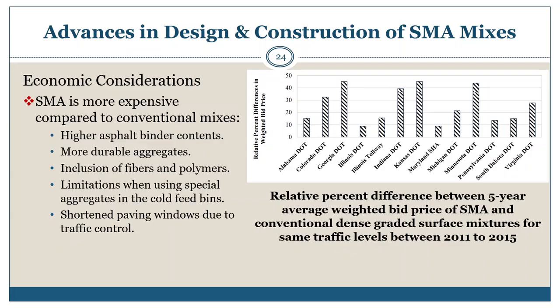Just about all agencies have reported that SMA mixtures are consistently higher in terms of initial cost than conventional dense graded mixes because of the higher binder contents, more durable aggregates, inclusion of fibers and polymers, limitations when using special aggregates in cold feed bins, and shortened paving windows due to traffic control itself. The relative difference between a 5-year average unit bid price of SMA and conventional dense graded surface mixtures for the same traffic level shown in the bar graphs are from 2011 to 2015.